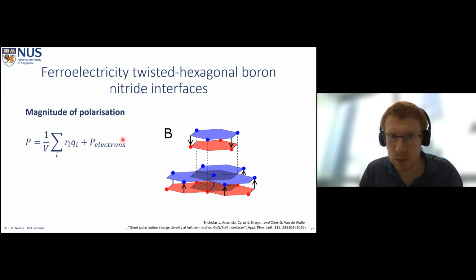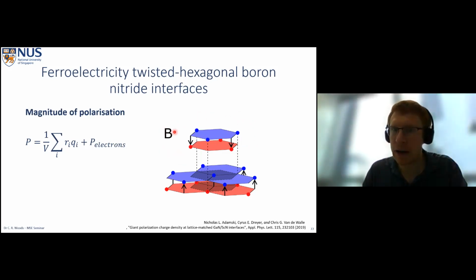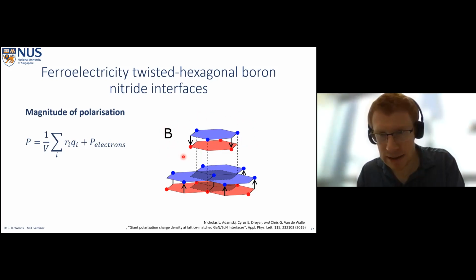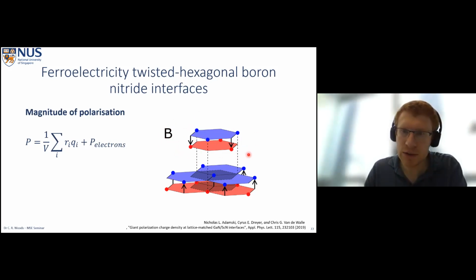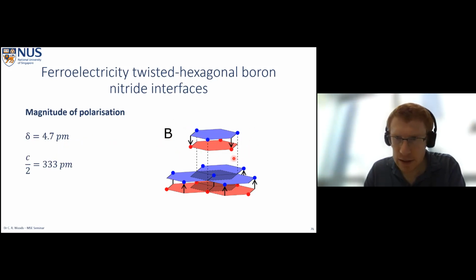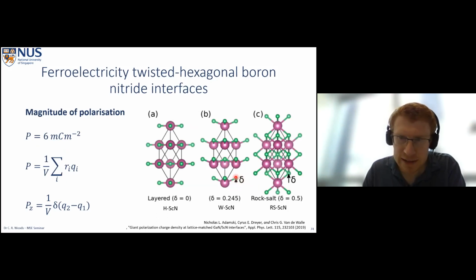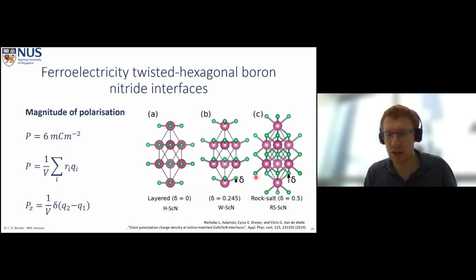In reality, they're both probably present. So how could understanding that help our experiments? Well, you might think about the other III-nitride systems, because what they do is they include different alloy amounts of, say, gallium or aluminium or indium, and they can change this distance. If I go back here, they can change this delta parameter by just changing the amount of, say, gallium they use compared to aluminium or something like this. And they get different polarizations, of course, depending on the different displacements here.